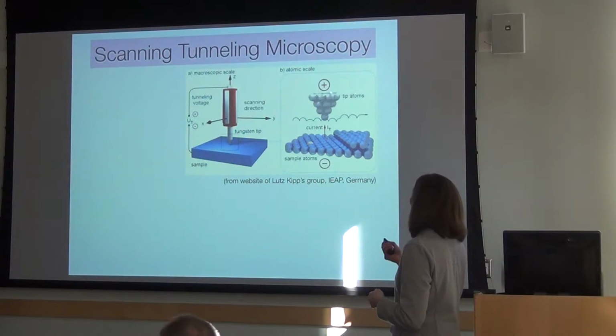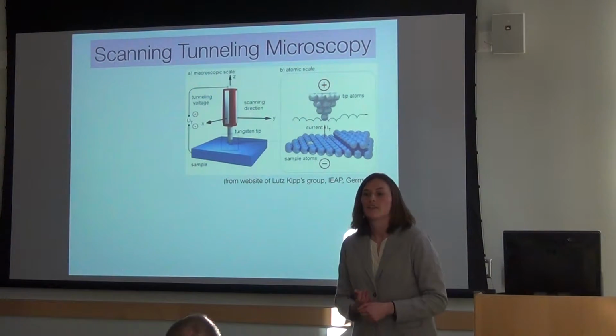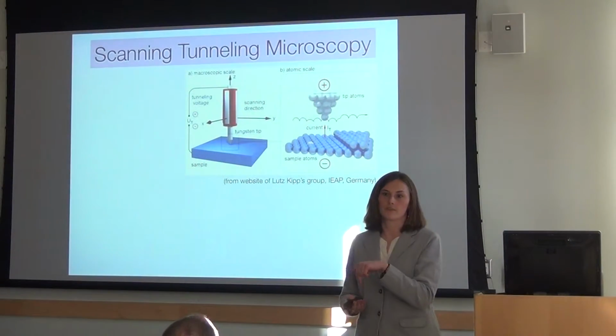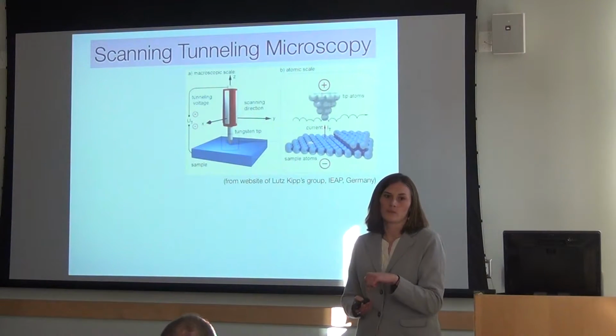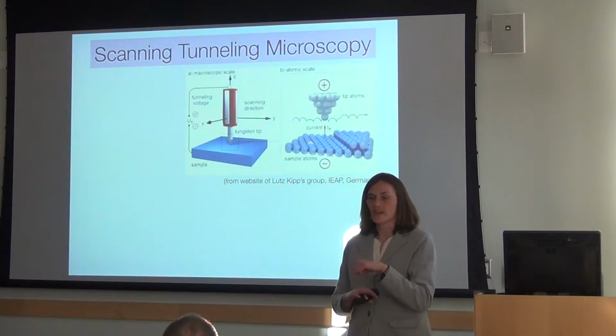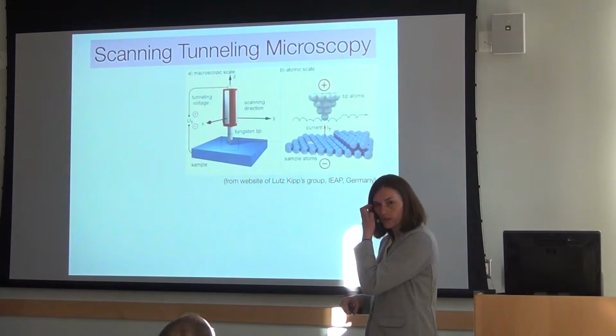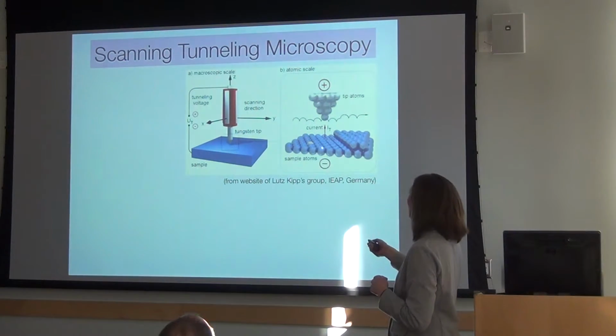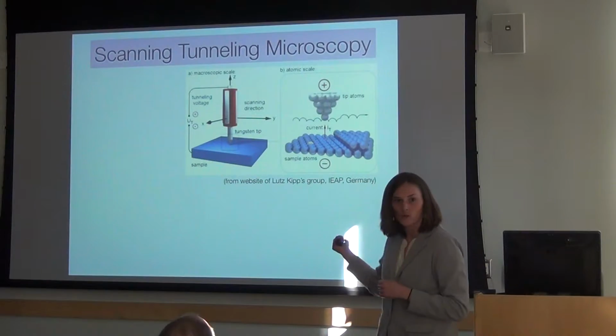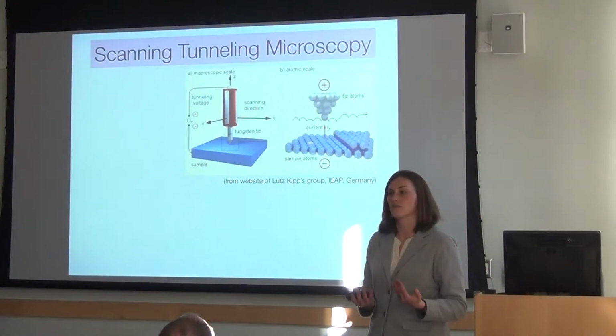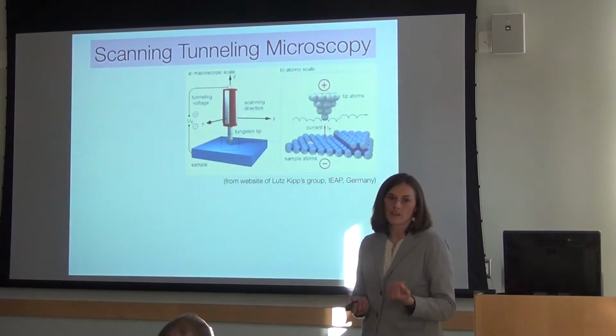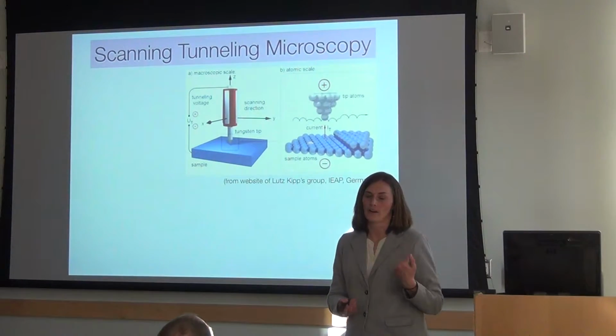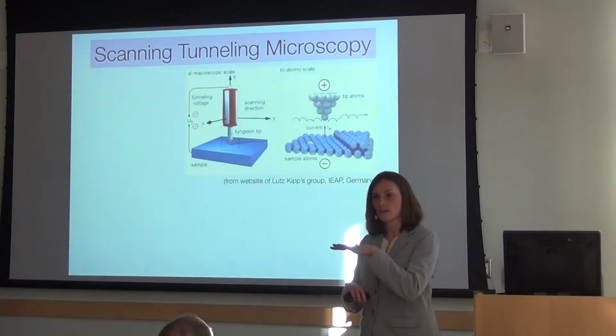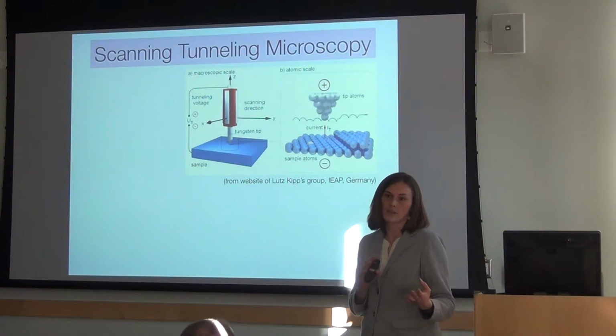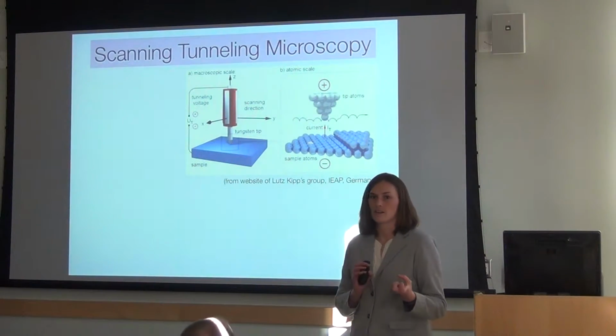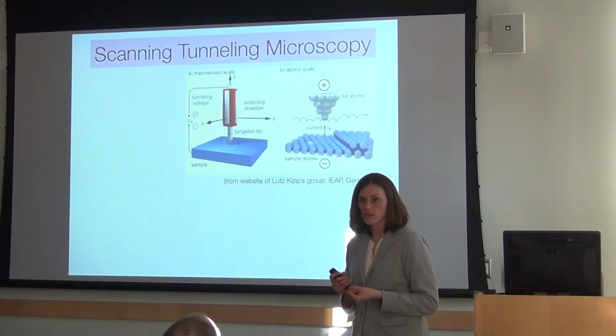And in particular, since you're using electrons to probe the distance to the surface, they're also going to be a probe of available states in the material. So if you were to image over this gold atom, say, maybe that gold atom has a higher density of states for electrons, so it would look like you would have a higher tunneling current there, and that wouldn't correspond to a change in height.